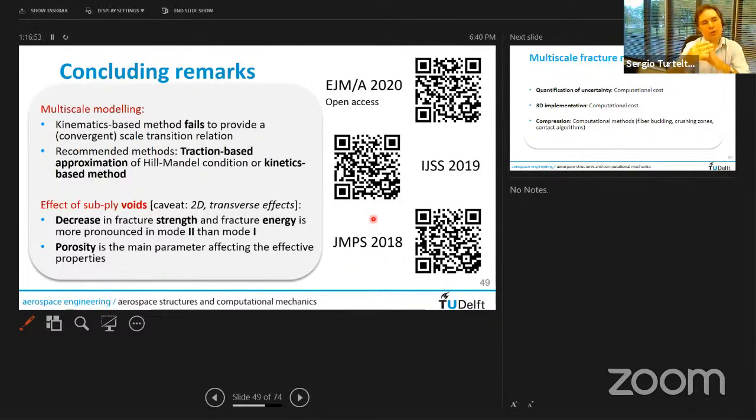Because those would generate distinct types of cracks. You would have transverse cracks, you would have delamination ones, and then all sorts of names for tunneling and so on. They are distinct fracture mechanisms. Technically, there would be an infinite possible number of combinations of all of those, and those cannot be superimposed. So it points to a certain limitation of this approach, which is that you have to consider all possibilities a priori, and it's an infinite number of them.